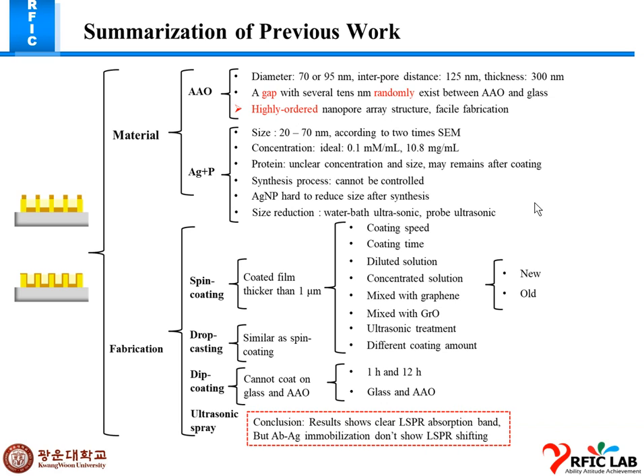So it's just a kind of sophisticated material on the glass. And the Ag nanoparticle with the protein complex is 20 to 70 nanometer according to the SEM, and the concentration is 0.1 millimolar, which is 10.8 milligram per ml. And the protein concentration is unclear, because there is no specific concentration; we got it from another lab. The synthesis process is also not controlled.